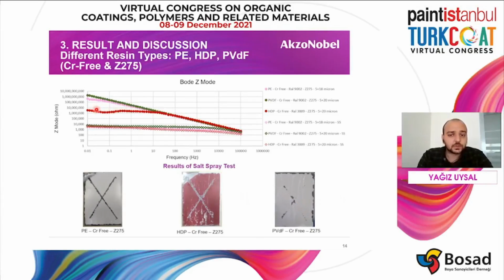And we can continue with the comparison of the polyester and high durable polyester. It was expected that high durable polyester coating would have a higher impedance value, but actually it is not. The reason for this behavior is that the high durable polyester coating contains red organic pigment. If we look at the result of the measurements of the panels after the accelerated test, PVDF coating has higher impedance value again.